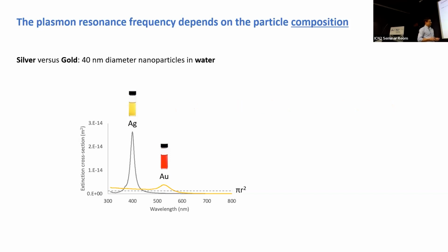Another thing that is really impressive of this plasmonic nanoparticle is that here I'm plotting for a 40 nanometer diameter particle, pi r squared. And it's this dashed line over here. So this is the geometric cross-section, and this is the extinction cross-section. What this says is that at 400 nanometer, a silver nanoparticle in water of 40 nanometer in diameter casts a shadow, an ideal shadow in a screen behind it that is several times its size.